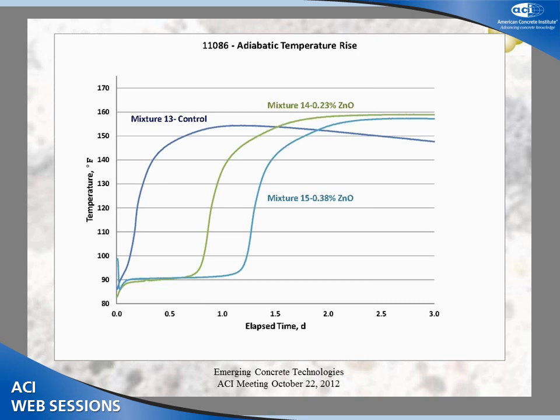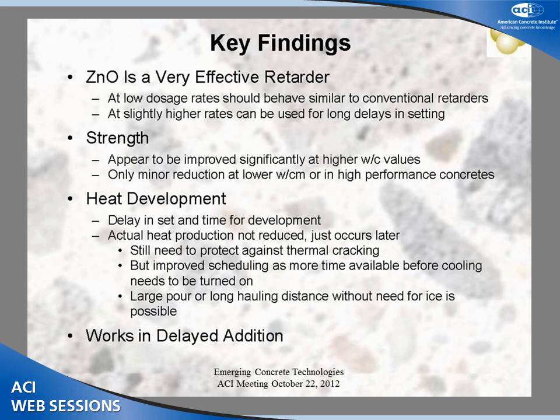Okay, there's two things that you would want to look for in a mass concrete mixture. You would want to have a mixture that has, number one, slower setting properties so that you don't get any cold joints in a large mass pour, and the second thing being proportioning it with a set of materials that impart the lower total heat of hydration. In the case of this work, we did achieve the hydration control where we can reduce the possibility of getting cold joints in a large 1,000 or 2,000 plus cubic meter mass element, but the zinc oxide did not lower the heat of hydration. It basically just delayed the inevitable.